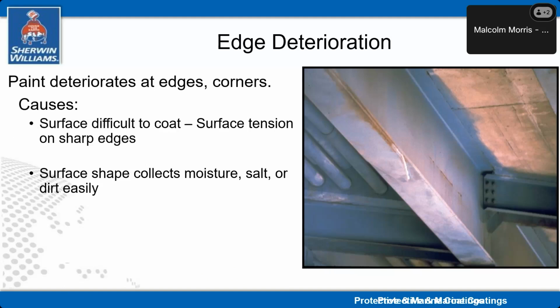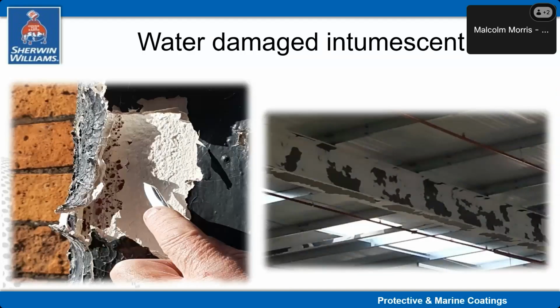But also it's a salt accumulation on horizontal surfaces, and that could also accumulate and accelerate the corrosion mechanism. Fire protection, I mentioned before, is very susceptible to water damage.